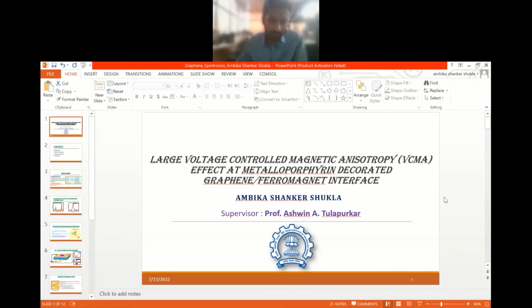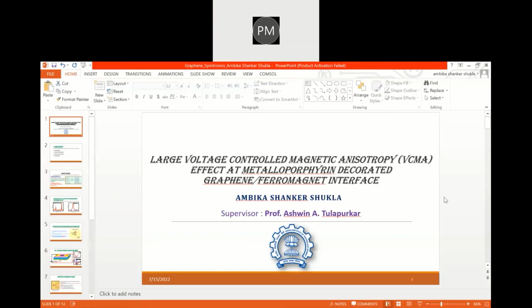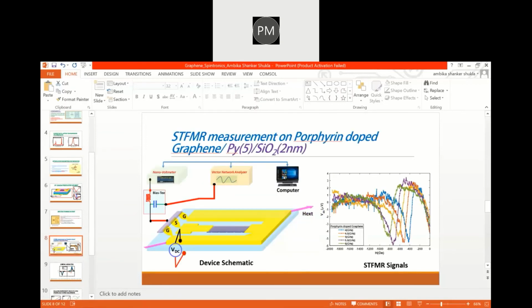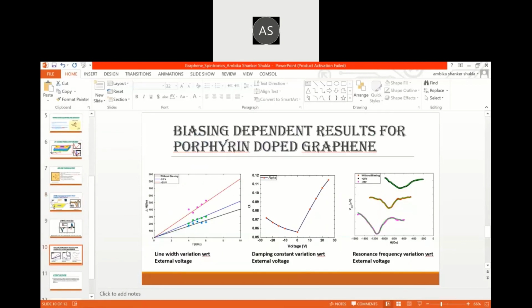Yeah, so I was wondering why all the parameters are being affected, because the resonance field may be because of, as you said, voltage control anisotropy, but why is the line width changing? So, Professor Pranav, currently I can say that this porphyrin, which we are using as an electron doping center for graphene and ferromagnet, creates a lot of electronic states in graphene, and that is probably responsible for this. But to answer this, we are doing more experiments with our PPMS, and we are still confirming this line width modulation along with alpha modulation. So we are still working on this.